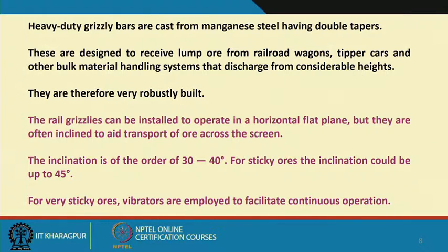So, it is not only the material handling system you are using and the point of unloading, it is also the material free flowing characteristic. So, you should know the flowability characteristics of the material beforehand. For very sticky ores, the inclination could be up to 45 degree, because more inclination means more momentum you can generate for the flowability of the material. So, when the material becomes sticky, that means you have more clay content in the ore, you can go up to a gradient of up to 45 degree.